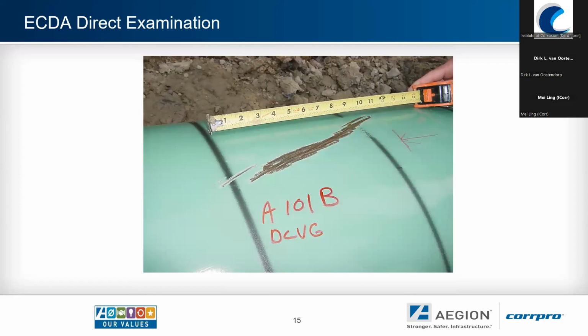From there, the next step is actually going down and doing the excavations after the surveys have been completed, areas have been identified. Here was a location where there was coating damage caused on the pipe. You can also see that there's gouges that resulted. It was a case where one of the cable companies was doing excavations and they crossed over this natural gas pipeline, hit and damaged the coating on the pipeline, and it was never reported. So the ECDA process did pick it up and identify it. When it was found to be aligned with some above ground markers from the communication cables, that's when it was prioritized for excavation, and also one that DCVG picked up very accurately as far as position.